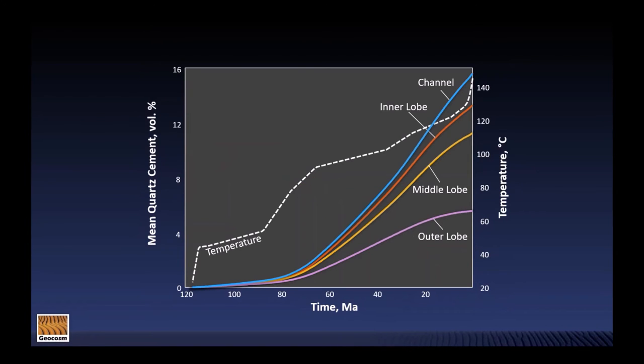So we see that indeed, the reason that we are having that slower rate of porosity loss in the outer lobe compared to the channel is that the rate of quartz cementation is different there, despite the fact that we have exactly the same temperature history in this particular setup here. So why do we see less quartz cement in the outer lobe compared to the channel?